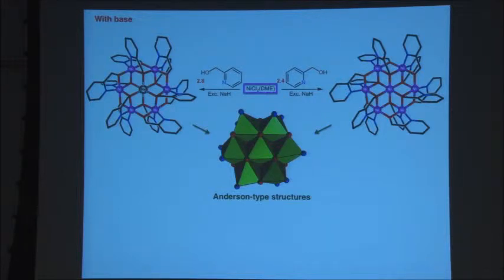Now, if you take the same precursor as before, and we go for the C1 spacer, 2.8 equivalents or 2.4 equivalents, with the same base as before. Here we find another kind of structural arrangement, which is a planar structure. All the nickel atoms are in the plane of the screen, forming kind of a wheel with a nickel in the center. And again, here you can easily recognize incomplete cubanes sharing elements between them.